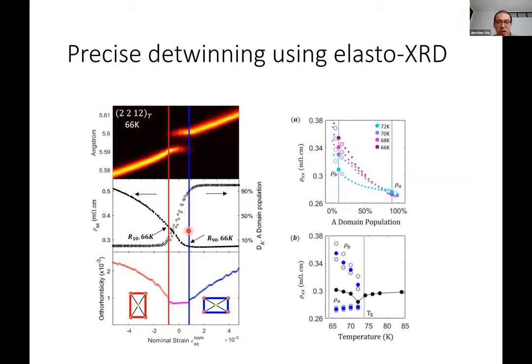So we're interested in measuring the spontaneous resistivity anisotropy in the crystal, which means that we want to measure the crystal in a state that is just fully detwinned, but not fully strained with external stress or external pressure. So we're carefully monitoring this twin population where we're just reaching the full detwinning but without change of lattice constant, and then identifying rho A and rho B, one corresponding to the resistivity at this point and one at this point, for each temperature. Now we can plot rho A and rho B as a function of temperature in the strain-free single domain states.